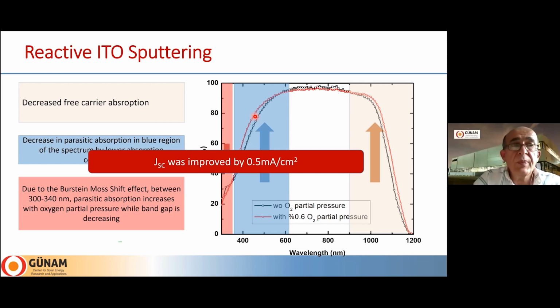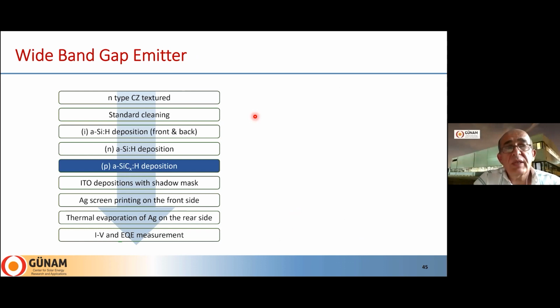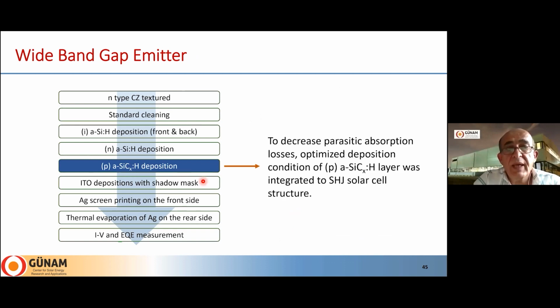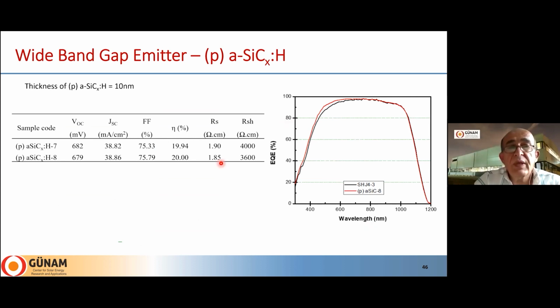technology development. But later on, we looked at the use of silicon carbide on the front side, because silicon carbide has a higher band gap. So it means that we decrease the parasitic absorption on the front side. Okay. So we tried to find the best process conditions for silicon carbide. And finally, we have reached these values. So we have reached an efficiency of about 20% with silicon carbide.